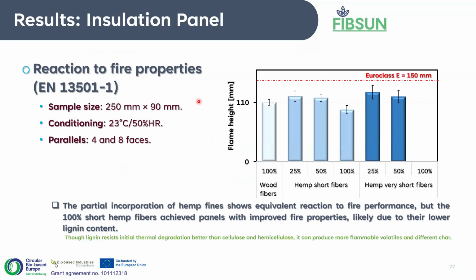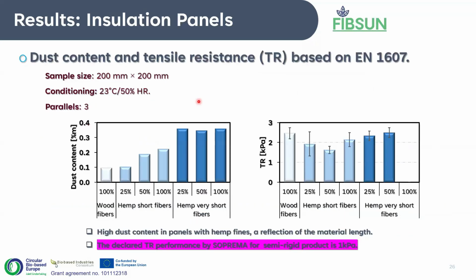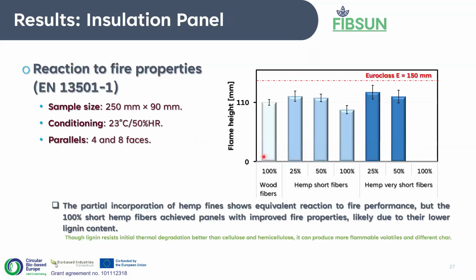And in this case, we see the same situation as with the perpendicular tensile test: even though there are variations, all our products achieve the target, which is the 1 kilopascals that Soprema already has as a base target for this kind of product. In the case of reaction to fire properties, lignocellulosic material in general, without any fire retardant or treatment or whatnot, will always react with fire. So this is just common knowledge.